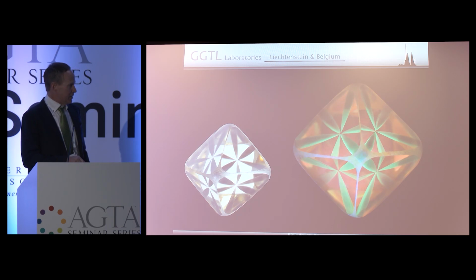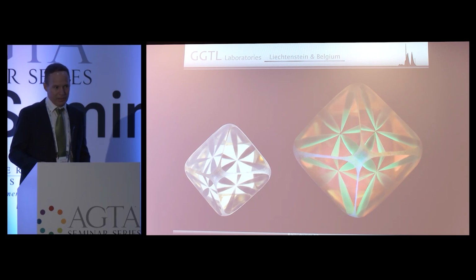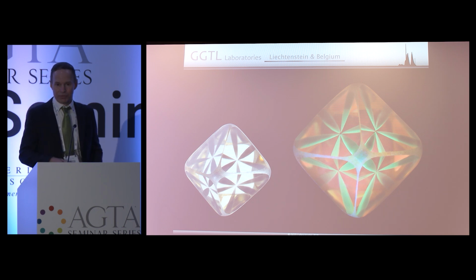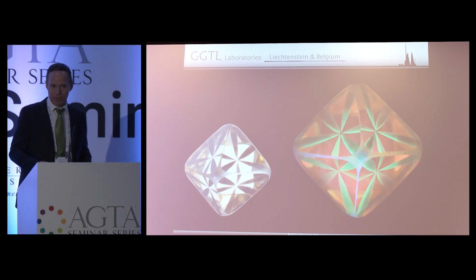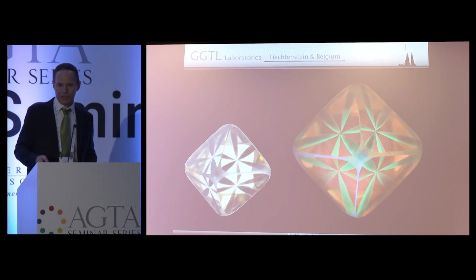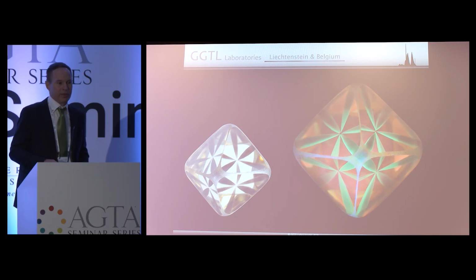The cuboid sectors accumulate different defects than the octahedral sectors. That's why the cuboid sectors fluoresce green. That's from a nickel-nitrogen defect. That's why they fluoresce green. And the rest of these stones is generally inert. When you look at most of the material in the market, you'll see that they're generally inert. You have just the green sectors. The rest of the stone doesn't fluoresce.